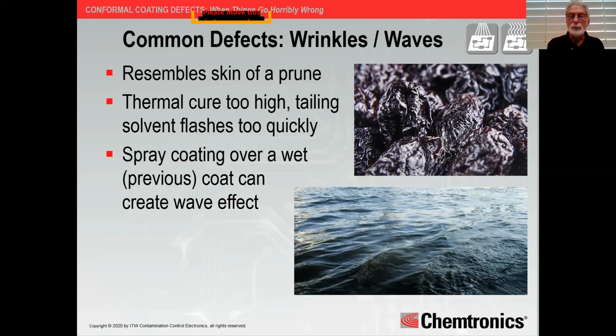If your previous coat is still wet and you're coating over that, instead of letting it come to a tacky condition first, it can create that wave effect like we kind of discussed before. It's just kind of pushing that coating away from that point of contact, and it looks like waves lapping over one another. And again, this is a condition that can be a defect. The question to be asked, according to 610, is does it ensure the form, fit, and function of that part in its service environment?